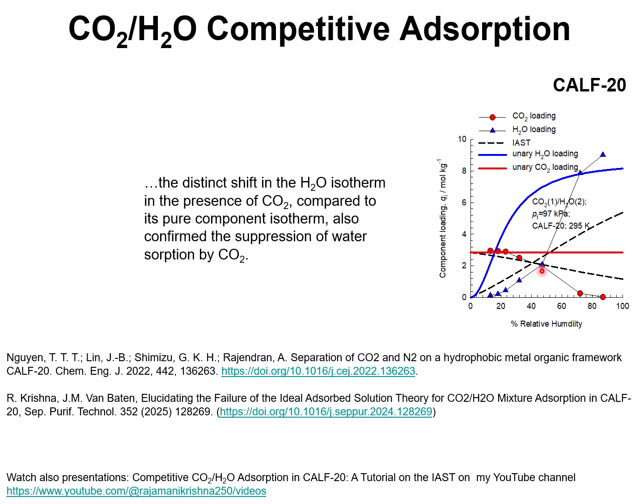For higher percentage humidities, we see that the water loadings are higher than the IAST estimates, and the suppression of water is not operative at higher values of relative humidity. Be that as it may, we can conclude that for relatively low values of percentage relative humidity, say less than 45%, there is suppression of water, and this is a persuasive advantage for use of CALF-20.